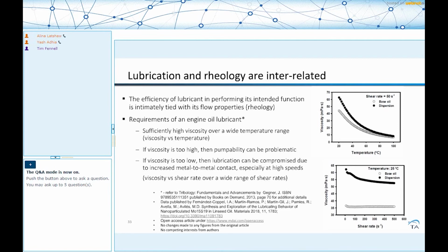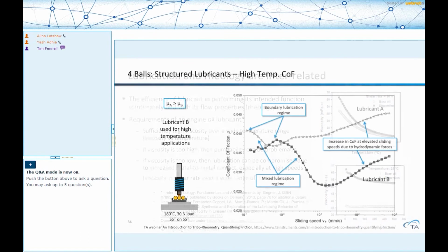So here, for example, we're showing some data where the researchers took base oil and they added some additives, which changed the flow properties of the material. The viscosity became higher, and while the base oil was Newtonian, the dispersion itself showed a slight amount of shear thinning, and this could be desirable, this could be undesirable, depends on the situation. But without knowing the flow properties, just looking at the lubrication properties will not give the complete picture. Vice versa, if you just look at the flow properties and don't look at the lubrication properties, that's also going to be incomplete. And so this is an example, we won't go into a whole lot of details.